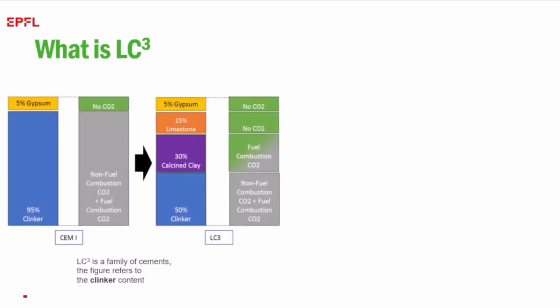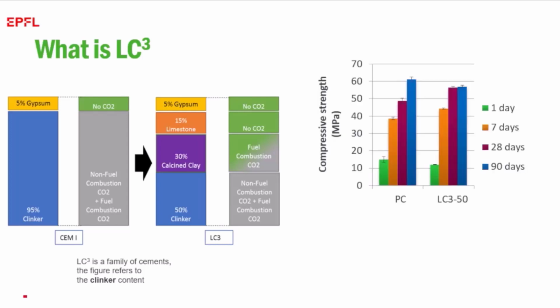And this just explains why we reduce CO2, because we replace the clinker by a combination of calcined clay and limestone. Limestone, virtually no CO2, and calcined clay, very low CO2, a little bit of CO2 from the fuel to calcine it, but this is about 10 times less than clinker, and eventually we can see this process being electrified. And the really interesting thing is with this combination, in as little as 7 days, we can reach the same strength as the reference Portland cement. So you've got the same strength really quite quickly.